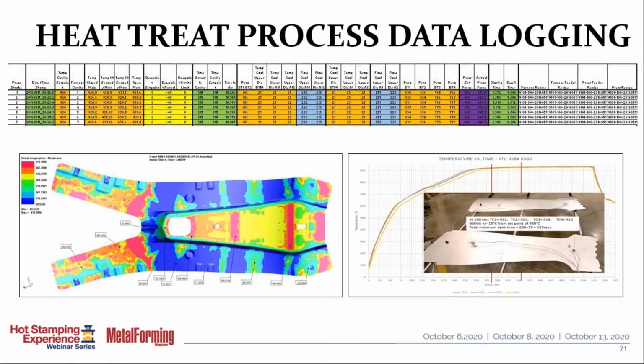And then we set a maximum time that makes sure that we protect the coatings and the inner diffusion layer from excessive growth. And then that becomes the nominal process requirements for the first step in the process, which is heating the material and austenitizing it prior to forming. The second step in the process is the quench process, where we have to determine what's the minimum tonnage that's required to properly quench the part in the amount of available time or the desired time, and we want to minimize that time and tonnage because it's beneficial to the tool.